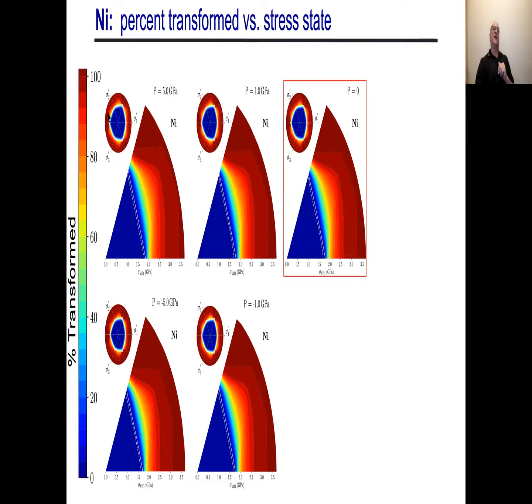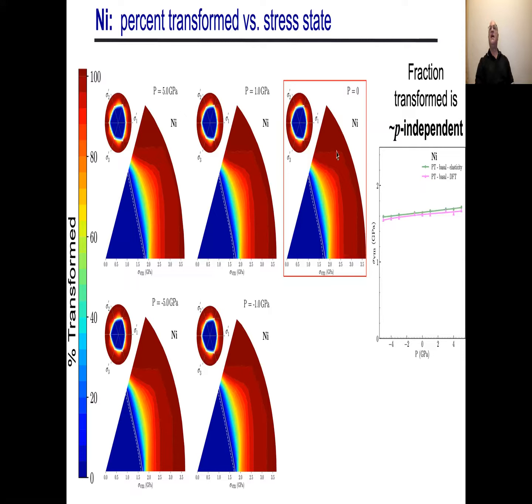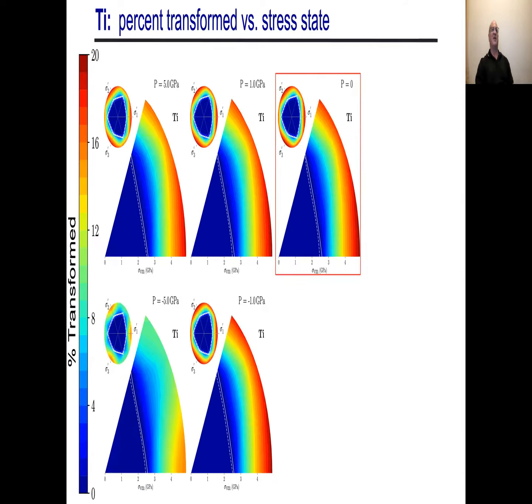And nickel is an interesting case because first, these are stresses that go from +5 GPa compression to -5 GPa, which is hydrostatic tension. I'm not sure if one could do that in an experiment, but probably not. But the point is, one of the things you see here is that in nickel, because I'm going from a close-packed structure to a close-packed structure, FCC to HCP, there's very little shear stress dependence to it. So it's almost pressure independent. The shear stress needed to transform is almost pressure independent. And again, DFT seems to work well.